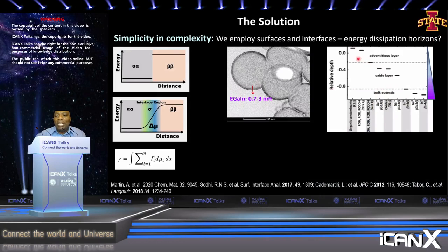It's actually a concentration gradient and is composed of different oxidation states, and the distribution of gallium and indium is almost speciated. You have a lot of gallium at the surface, but as you go to the end of that oxide, you find you have more indium. So these set up a question.